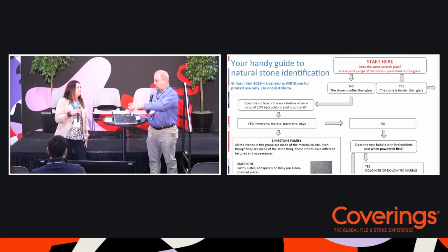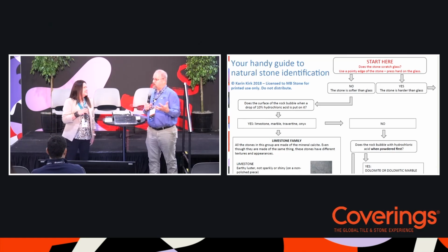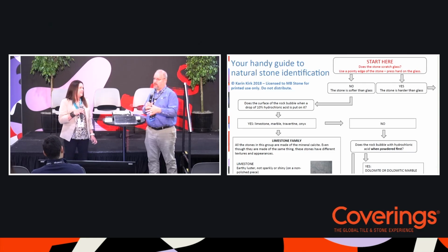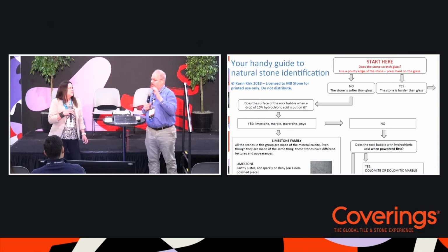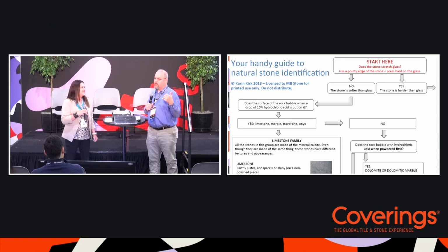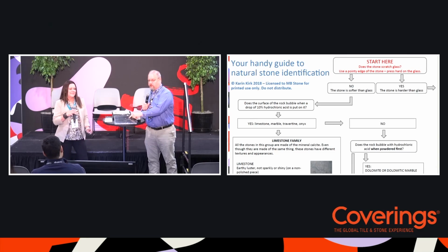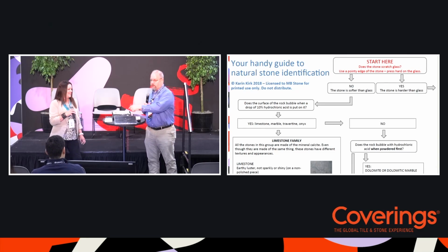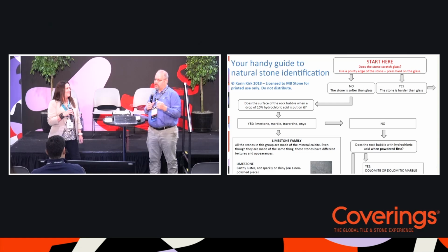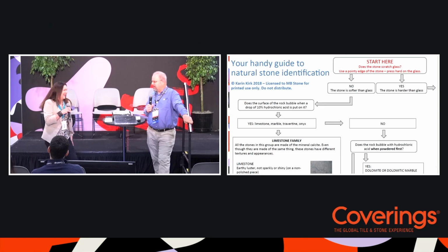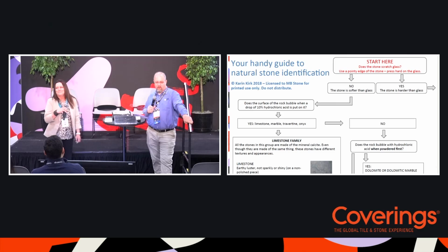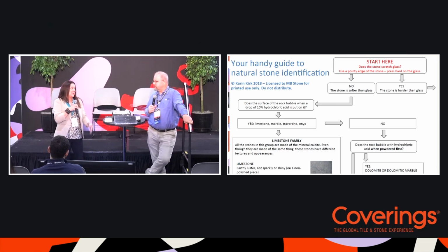Your colleague Cameron and others before him many years ago told me a very general guideline, a very broad generalization, when you see a discoloration in the stone. If it's lighter than the surrounding stone, like here you see a lighter spot, that's going to be an etch. If it's darker than the surrounding stone, then it's likely going to be a stain. So if it darkens or looks wetted, that will be a stain. That's from our care guide. Decades ago, yes. Very general, but I haven't seen anything where that doesn't hold true. It does.